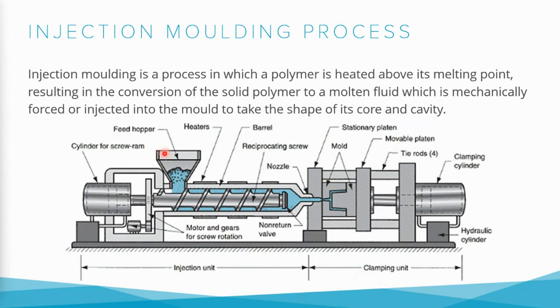We put plastic material into the feed hopper. The plastic material is then inserted into the barrel, which is in a heated condition. There are three zones inside the barrel. The first zone just below the hopper is called the feed zone. The next zone is the compression zone, and at the end we have the metering zone. The feed zone receives material from the hopper and conveys it to the compression zone. The compression zone compresses and mixes the material. The metering zone then conveys the material from the injection barrel to the mold.